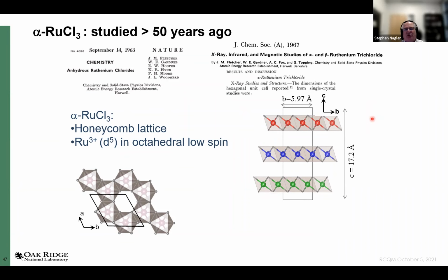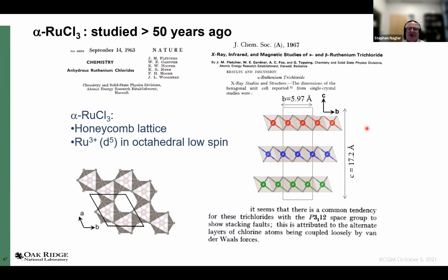Let me come back to the crystal structure in a second. I'll just say this is a very two-dimensional material where the layers are just held together by van der Waals interactions. And that being the case, you can get, in principle, a lot of stable structures, kind of like a clay, different stackings and so on. It was recognized very early that there's a tendency for these things to form stacking faults. And if you look in the literature, you'll see all kinds of slightly different refinements of the crystal structure. So that's been an issue with this material for a long time. It's very easy to slide one plane over the other without doing much except changing the stacking sequence. The stacking sequence at low temperature seems to be threefold, but exactly what the structure is turns out to be tricky and can vary from sample to sample.